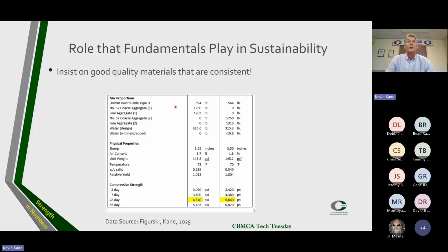So we made our first mix. We gathered an aggregate sample from a local producer right here in the Front Range. We didn't particularly like the sample of coarse aggregate that we got. The gradation was way too fine. It was pretty dirty, but we ran the mixes anyway. And we ended up having to discard the whole series because we didn't like the results we got.